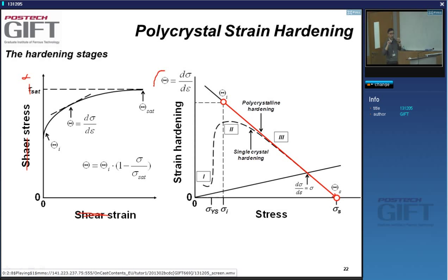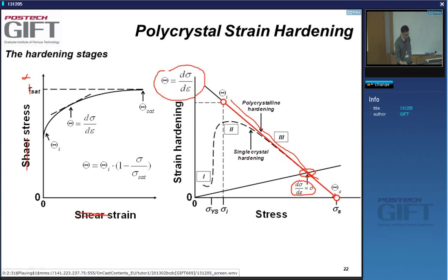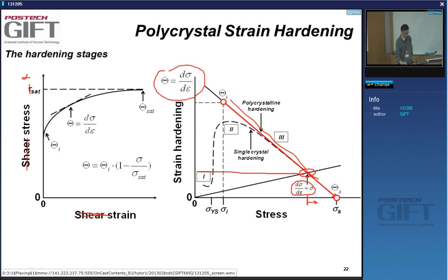If you plot the strain hardening, in general it will always go down. Now, why are we so interested in this strain hardening? Because of this point here where the strain hardening is equal to the stress — that is the point where we have the maximum strength and the maximum uniform elongation. We want to increase this point beyond the current value of strength and strain hardening. So we need ways to increase the strain hardening, and it's very difficult.